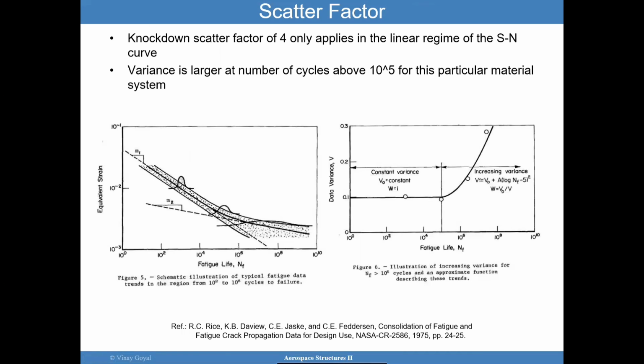The scatter factor of 4 only really applies in a linear regime of the S-N curve. The variance is large at number of cycles above 10^5. You can see that here, the variance is quite significant. At 10^5, you can see the variance taking off. In other words, you could be quite off predicting fatigue life at those high values.